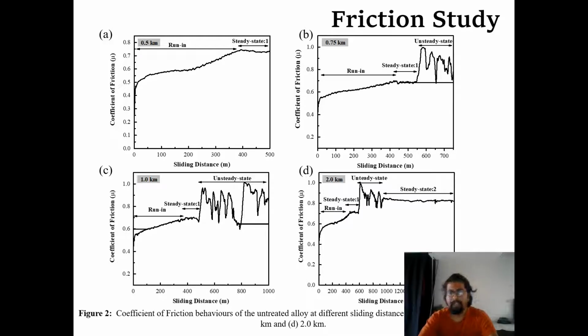So as I said, my main objective was to first understand the wear and frictional behavior of the untreated cobalt-chrome alloy. So here we can see the cobalt-chrome alloy when it was not nitrided, how it behaves. Starting at 0.5 kilometer, it was very much clean. We can see less disturbance, only the friction coefficient is increasing. At some point it starts stabilizing, and then as the sliding distance increases, the presence of oxide debris can be seen because of the waviness in the friction coefficient values.